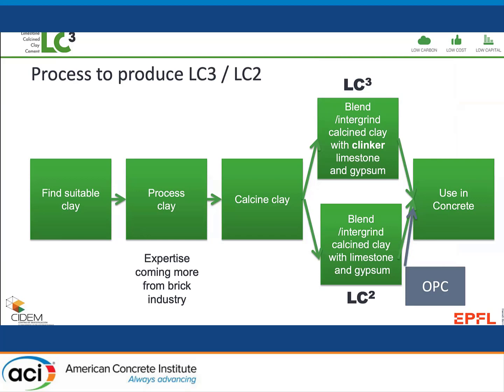So when we want to produce LC3, I think we have to bear in mind that LC3 is the idea that we take the three ingredients. We take the calcined clay with the clinker, the limestone, and of course the gypsum, and we grind them all together in the cement plant. But we can also do it another way, which is probably more suited to the North American market. We can take the additional SCMs, we can take the calcined clay with limestone, and it's important to add a little bit of gypsum because it's important to adjust the sulfate. And then that is a sort of package ready to go that can be added at the concrete level.